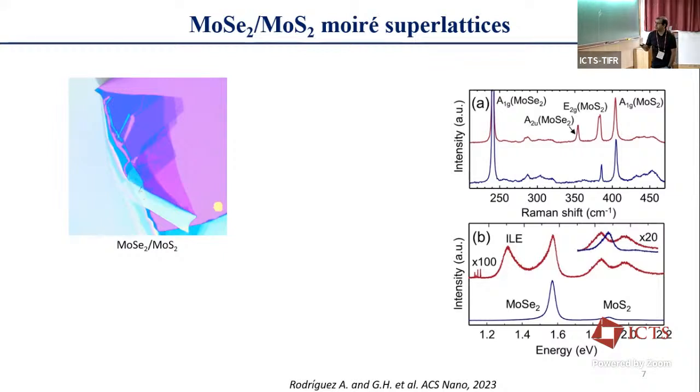Now, if we anneal the heterostructure a bit, then we start to see the creation of these two different triangles you can see in the middle. And this triangle is actually where the layers start to talk to each other. Now, if we keep annealing for a longer time and at a bit higher temperature, this will increase further, and the whole structure will collapse one after the other, and it will create Moire patterns all over the region.